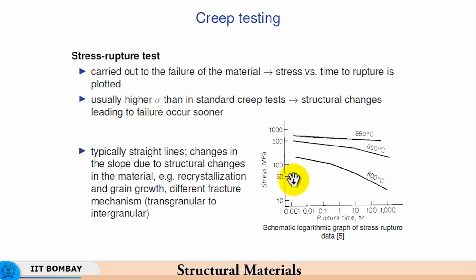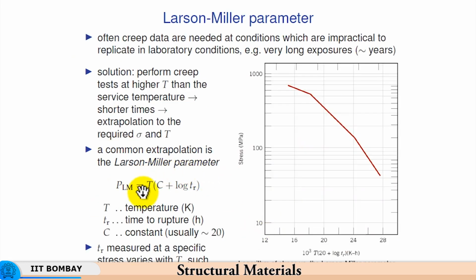So, what it means is that rupture time and temperature of testing both act in the same way on the stress, in the sense that the stress capability gets reduced with increasing temperature, and the stress capability gets reduced with increasing time, as the creep strain increases. That is the reason why we can combine the effects of temperature and rupture time into a Larson-Miller parameter,